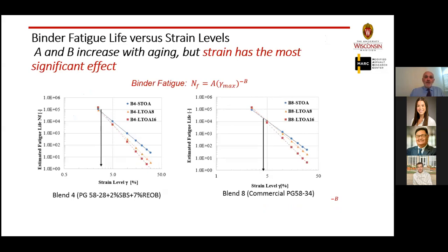You get this very simple straight line, relating the estimated fatigue life as a number of cycles. You can define this failure at 30% damage, 35% damage, which means a 35% reduction in the modulus, or you can make it 50%, or some of us pick a certain point on the stress-strain curve, like the peak stress, and calculate the A and B. So A is the intercept of this line, and B is the slope of these lines. Very similar to the M value in the IFIT procedure, but it's calculated in a different way. What you look at here is strain level, and I'm just covering this narrow range of 0.5 to 50% strain. But this is a classic fatigue behavior of many different materials, elastic or viscoelastic.